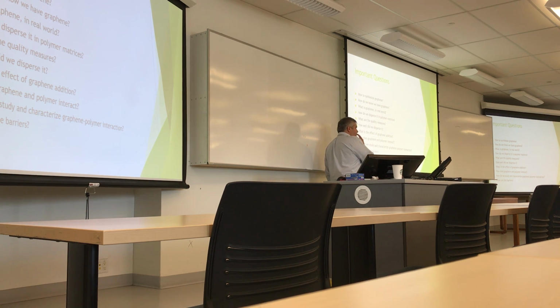And then we needed to know, okay, when we disperse, how well we disperse the graphene in the polymer. This is important. We don't want to have it somewhere and not have it somewhere. And then after we disperse it, what's the effect of graphene addition? Is it really better than CNT or not?